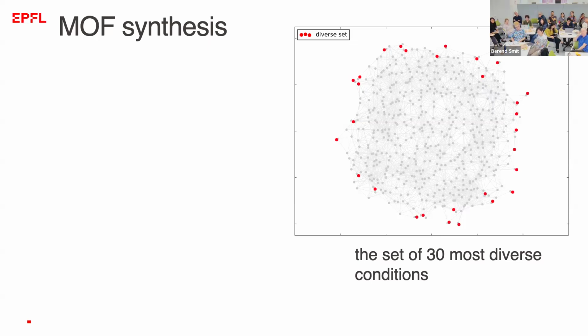And then we selected a set of 30 most diverse conditions by doing a min-max algorithm. You select one condition at random and the other one furthest away from it. And then the third one is the maximum minimum distance. So where can you put it so that it's as far away from this one and from that one, and the fourth? If you then look at that in very high dimensions, this UMAP is basically a projection on 2 dimensions of these distances, but in such a way that you maintain as optimally as possible that if 2 points are close, they're similar. And in high dimensions, the set of most diverse conditions are at the edge. So this is sort of showing that.